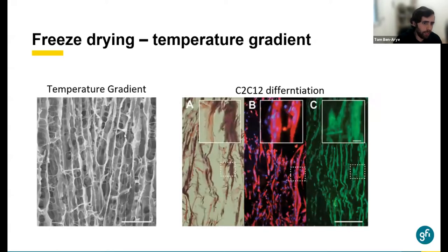In this paper, this is an interesting technique where you can basically generate these structures using a temperature gradient. This temperature gradient generates a directionality of the ice crystal formation, which results in a directionality of the polymer structure. And this is relevant for tissue engineering for growing muscle fibers, which differentiate better when having such a directionality.